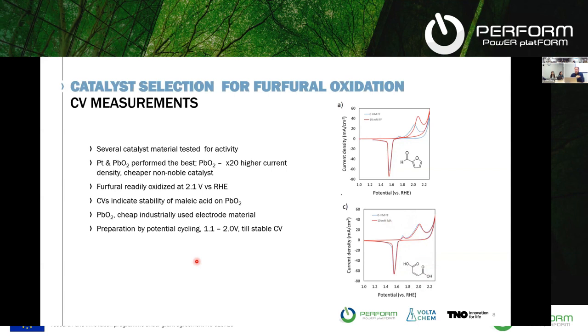So within this research, what we figured out is that platinum of course works nicely for this oxidation reaction. However, we also found that lead oxide works quite well, actually even better than platinum. And lead is a quite nice material that is already used a lot in industry as a catalyst. So we actually settled for lead as the main working catalyst.